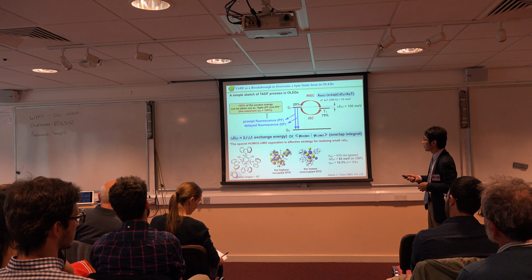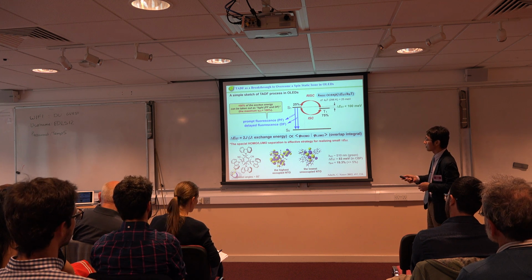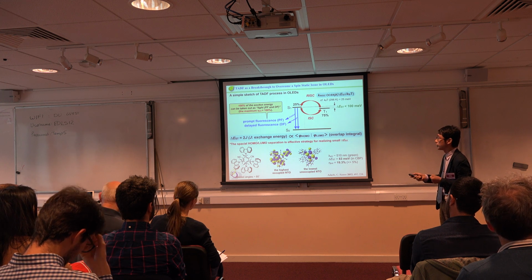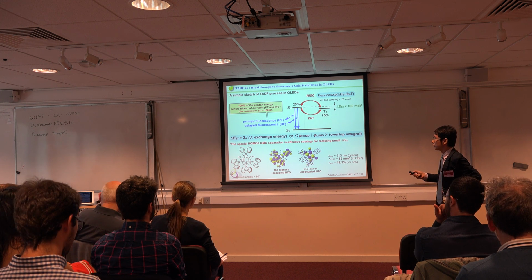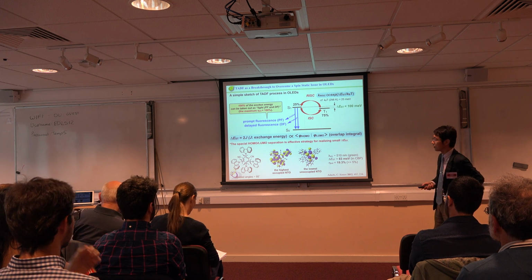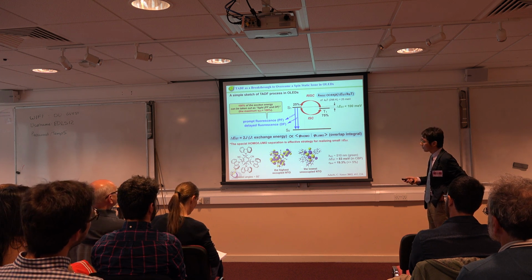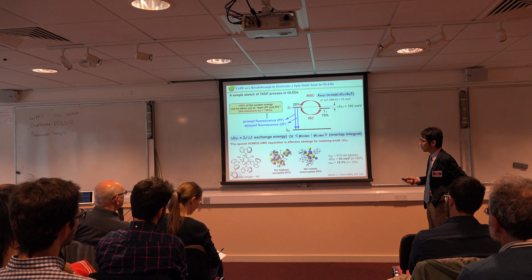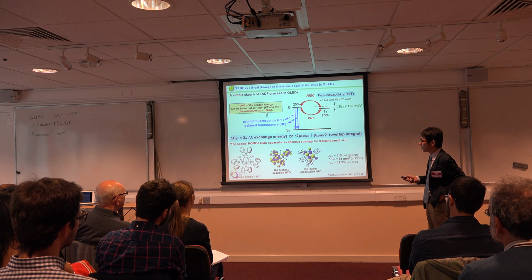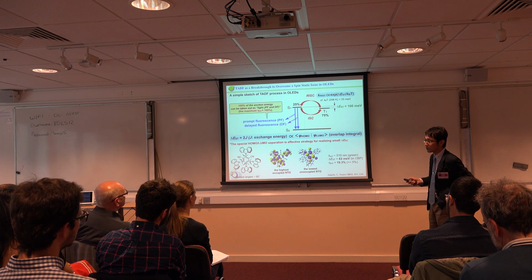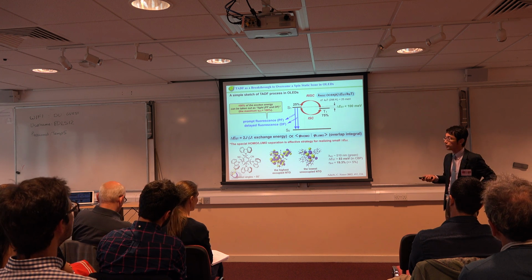As you can see here, the delta EST is proportional to the exchange energy, which is proportional to the HOMO-LUMO overlap integral term. In this equation, we indicate that when you separate the HOMO and the LUMO, such compounds can emit TADF.